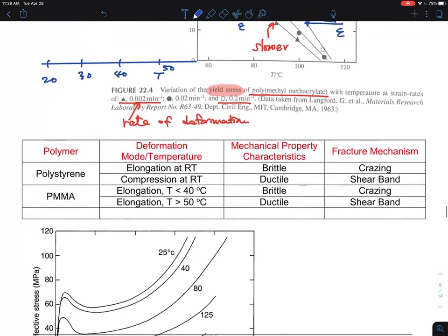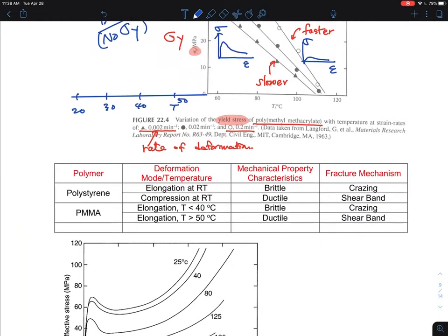I want to give out this example of this experiment result. And here's, I'm going to show something that polystyrene, I'm going to show it in more examples later. But if you do the typical elongation at room temperature, it is brittle. And the fracture mechanism that is going to go under is what is called crazing. So I'm talking about polystyrene being the glassy polymer. So is PMMA. When you see the fracture mechanism called crazing, which will be explained later in the video, the material turns out to be brittle. It would just a simple stretch and then break the sample. So as I said, that elongation at 40 degree or lower, or just the elongation at normal room temperature. And this is where you can see that.